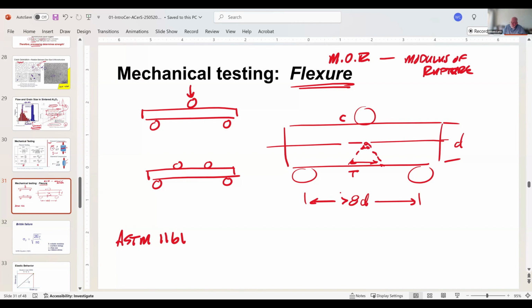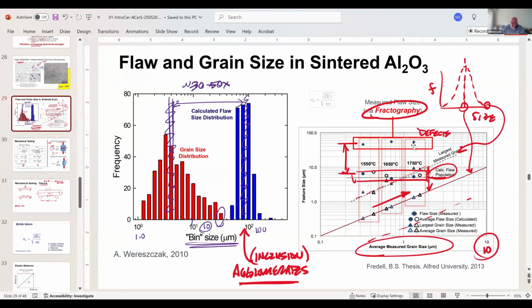Okay, if my flaw ends up here, my specimen fails at a lower load. If my flaw ends up here, and this one is not existing, this second flaw fails at a higher load, and this one, even for the same flaw size, will fail at a much higher load. So in fact, this would require a different flaw to fail. So where my flaw is located dictates then the strength. The closer to this surface, the lower the strength, which is why in Anna's data back here, her measured fractography flaw was much greater than her calculated flaw populations because of where that flaw occurred on the test specimen.